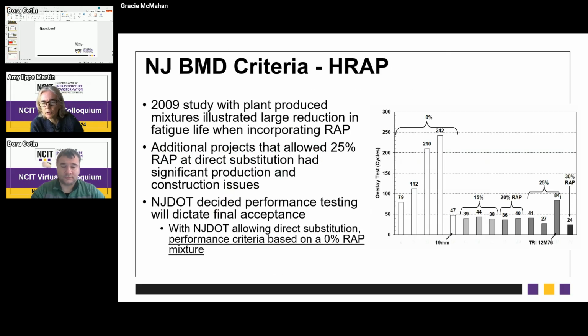So for the New Jersey or Rutgers part of the experiment, they first decided to bump up and allow projects to use high RAP contents. And they started seeing that there were significant issues in terms of fatigue life or cracking resistance with their repeated load test, the overlay test. You can see the big drop off in the solid colored bars there. And so they said, okay, we can't just allow this material to come into our mixtures without having a mixture performance test. So they decided they needed to introduce a cracking test and make sure that they're getting at least as good a performance as a virgin mix or a 0% RAP mix.